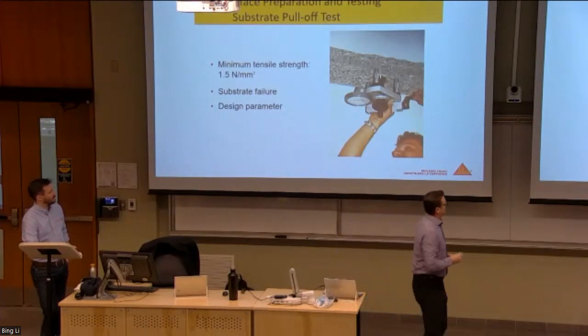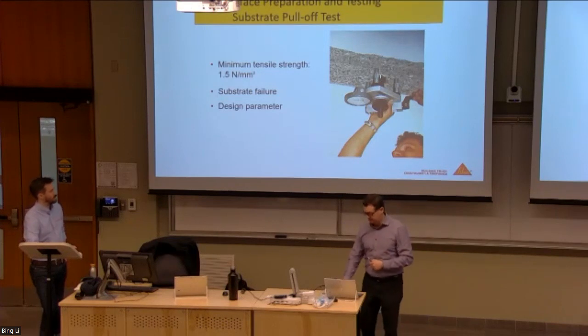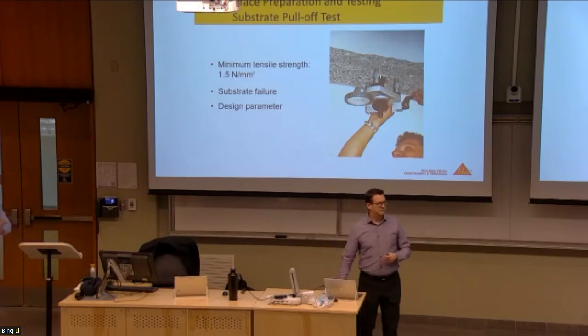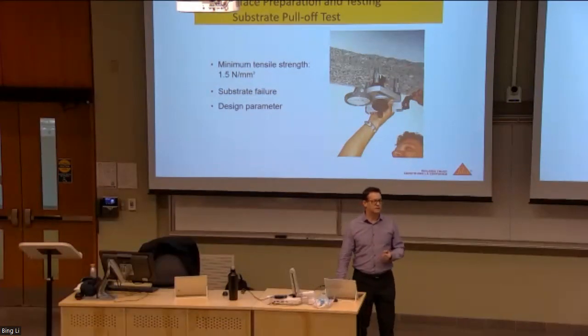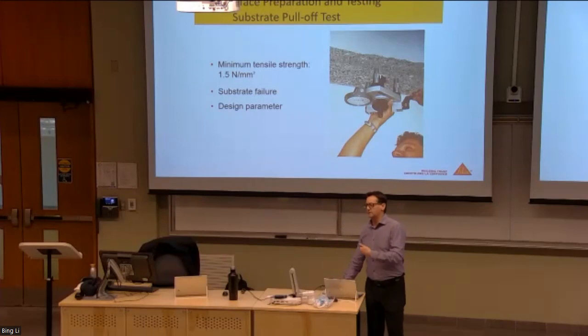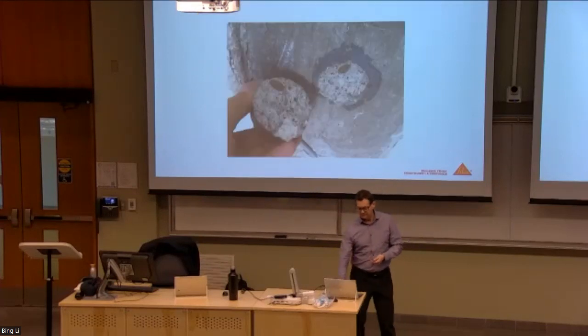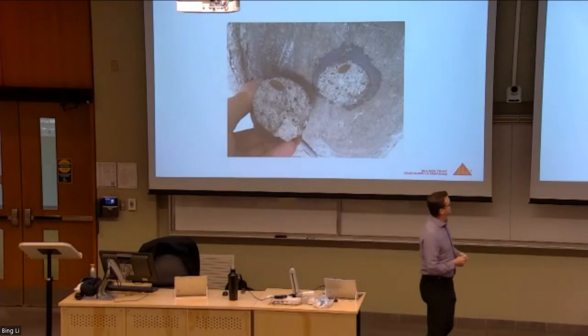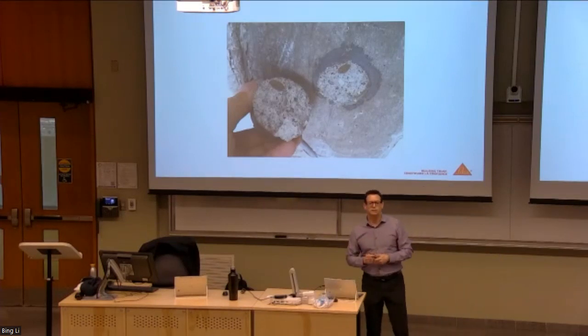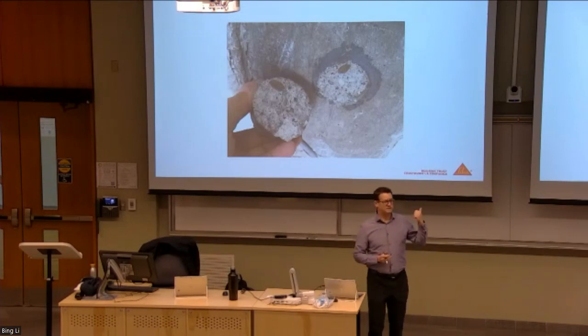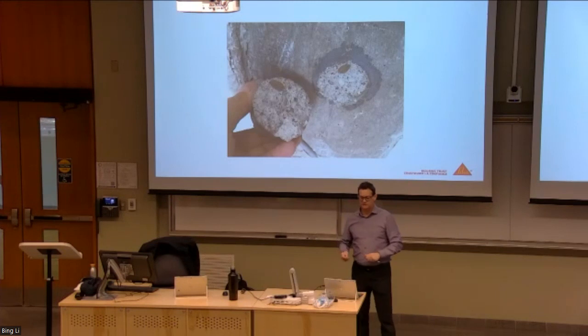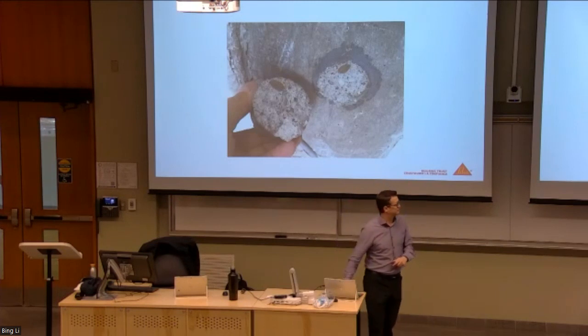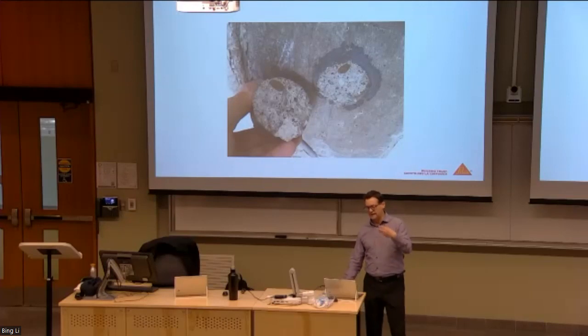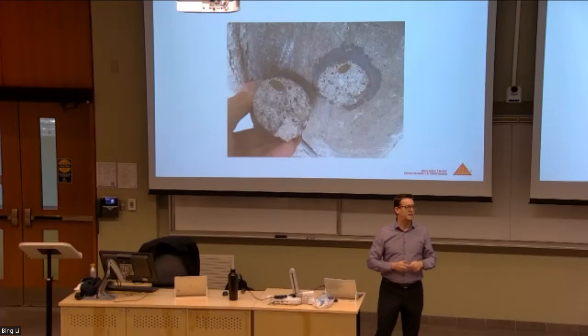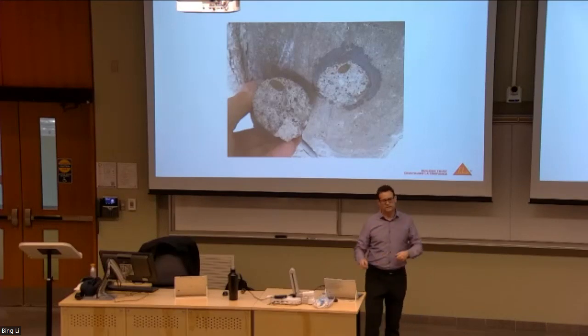This just shows you some of the things that happen on site. There's a mechanical preparation that takes place, and then we do some bond testing. Either the engineer or ourselves can do bond testing to make sure that we have a substrate suitable for the bonding of the epoxy and the products onto the surface. With the bond test, we want to reveal that the concrete has sufficient strength to support the installation. So we do a tensile pull test of these materials. We want to see a concrete cone failure such as this, to indicate that the concrete is in good shape to receive the products, and more importantly, to engage the entire structure with the incorporation of the carbon fiber.